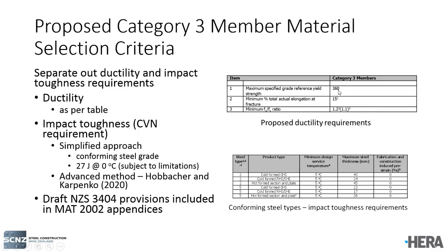It's equivalent to essentially a grade 350 steel. The minimum elongation at fracture has been reduced from 25% to 15%, and we have a minimum FU over FY ratio value of 1.2. The current requirements have FY over FU, so we've essentially flipped the ratio on its head. We have two requirements. One is if you're determining the FU over FY from the minimum grade requirements of the product standard, that minimum ratio is 1.2.